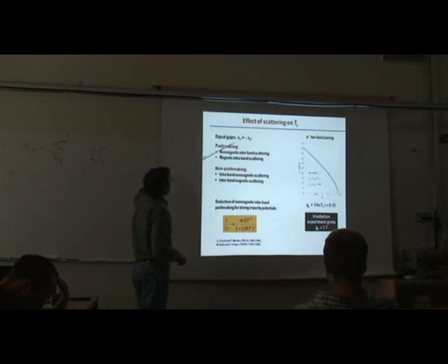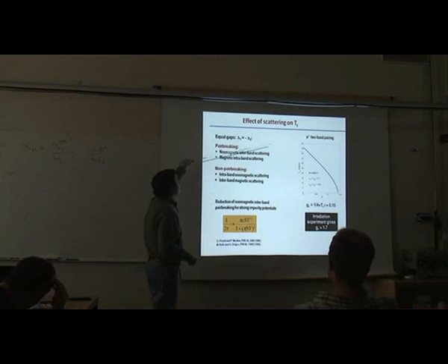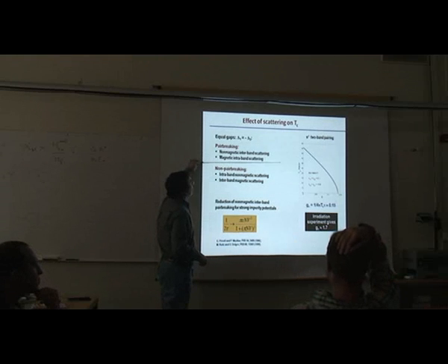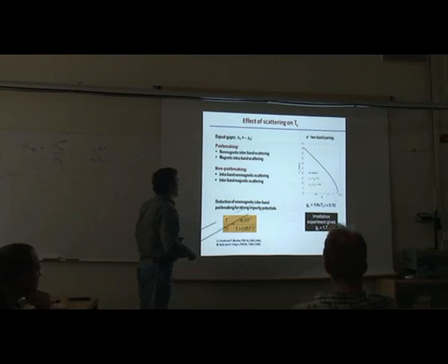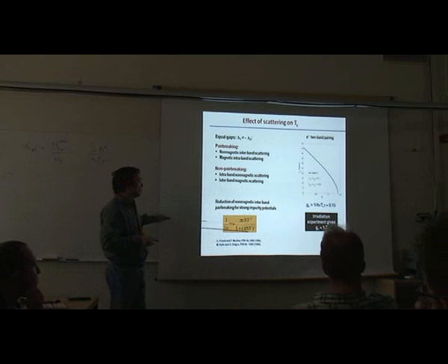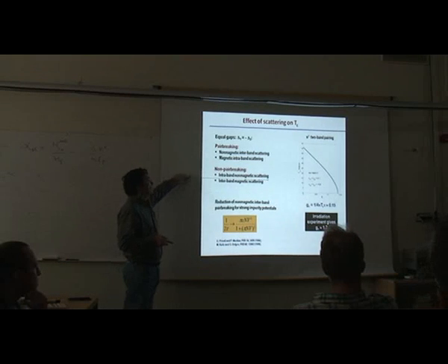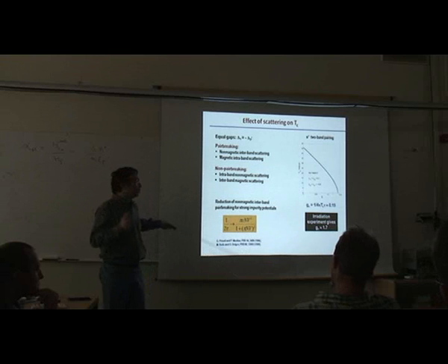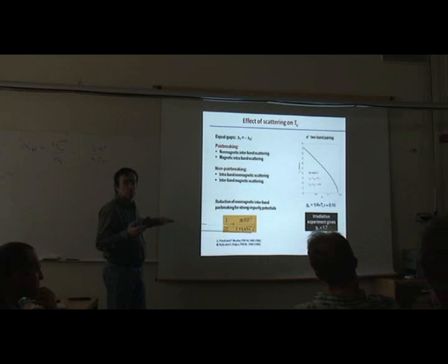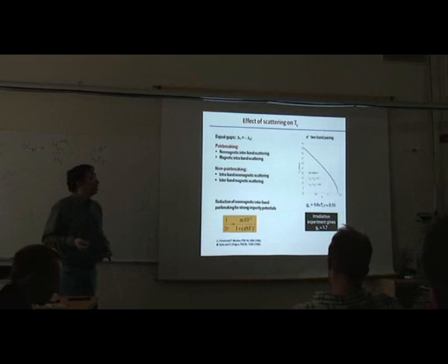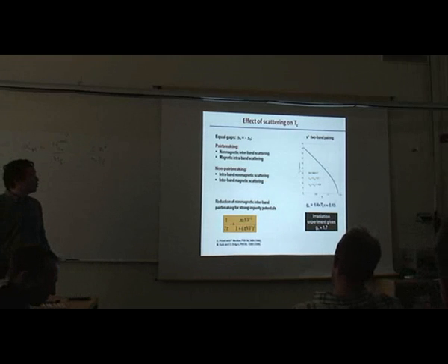Well, as I said before, if we have equal gaps with different signs, we have pair breaking scattering and non-pair breaking scattering. Pair breaking scattering is non-magnetic interband scattering and magnetic intraband scattering. And those are non-pair breaking. It's been shown that if you have sign change in the order parameter, non-magnetic interband pair breaking scattering is strongly reduced in the unitary limit, when the scattering amplitude is large. And this is a formula, so you can see that if this is large and this is large, you actually cancel the main part. So that reduces the effect of non-magnetic scattering. However, the magnetic scattering cannot be reduced. In fact, it becomes only stronger.